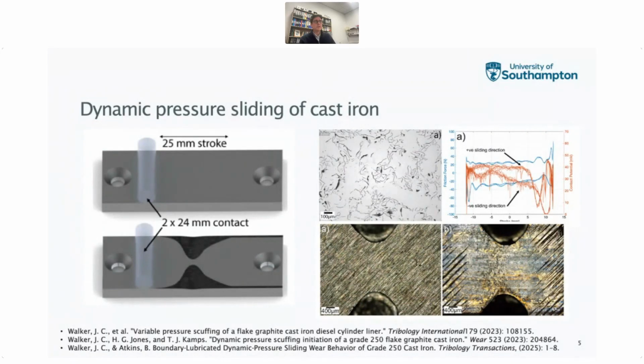So we've been experimenting with putting different profiles on our surface where we will subtractively remove material from the running surface such that we get a dynamic change in pressure as the coupon is sliding, reciprocating across that contact. And that's quite interesting because once you start putting these constrictions in, depending on where you put them, you could actually put it around here, for example, on the left part of the coupon, which would be closer to top dead center, which is actually where you see the increase in pressure from the compression and expansion stroke. And then you get very interesting behavior in the lubricant film formation.